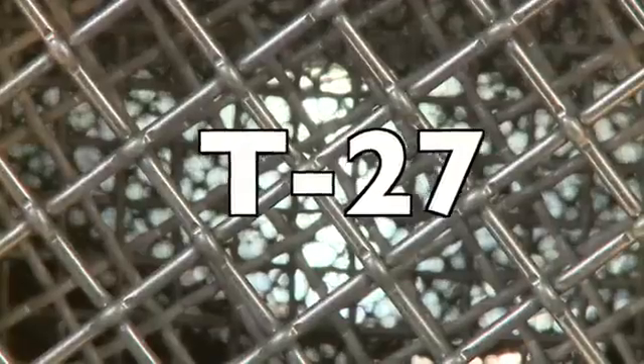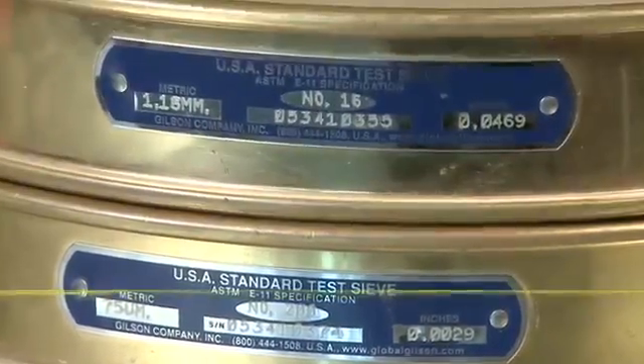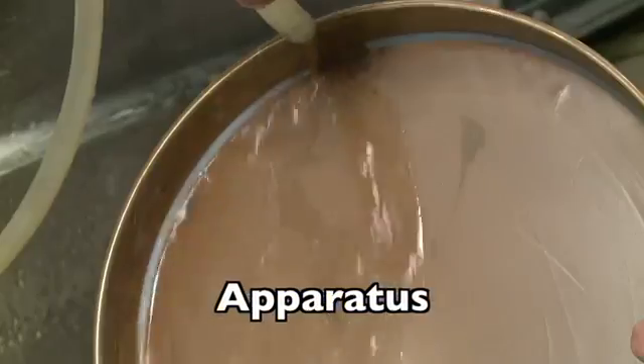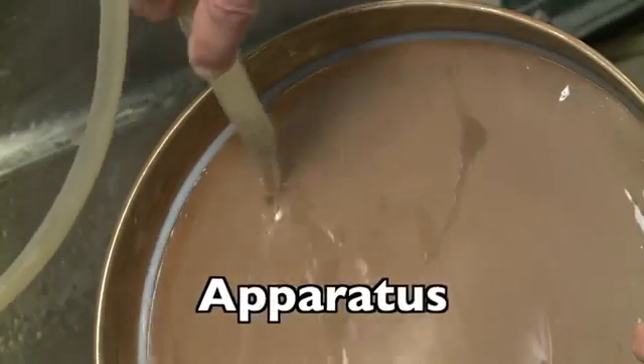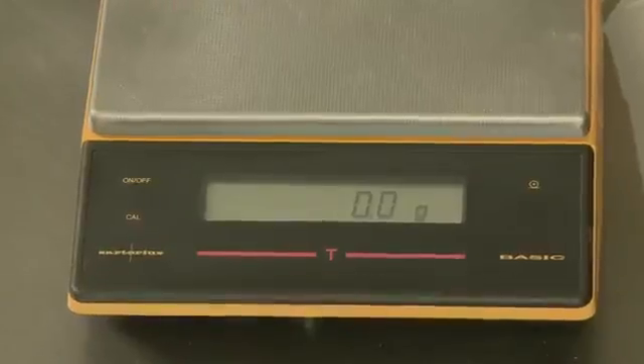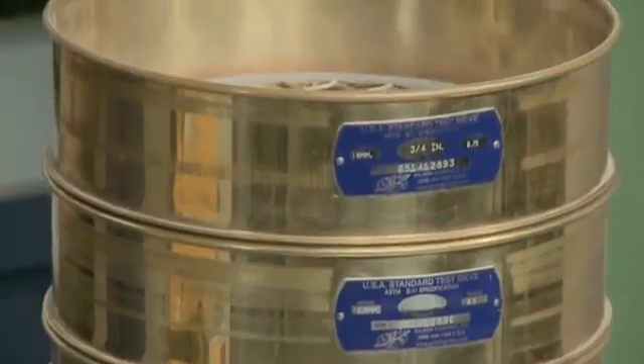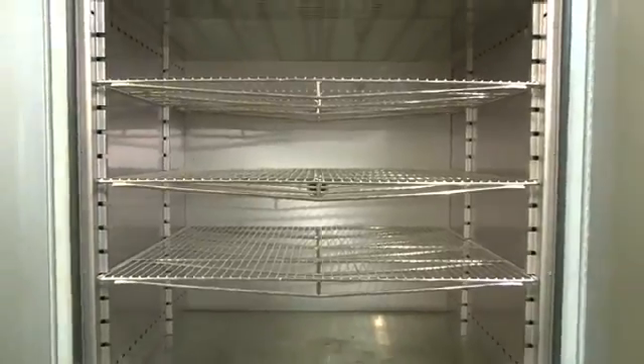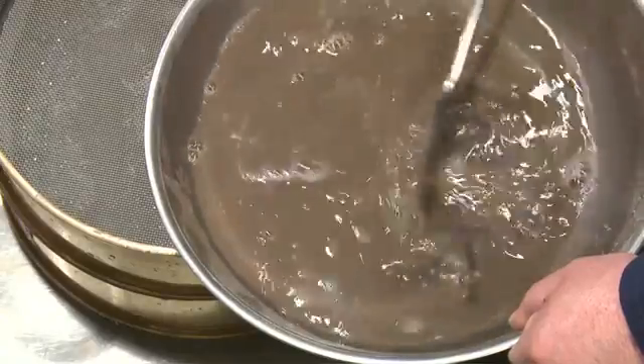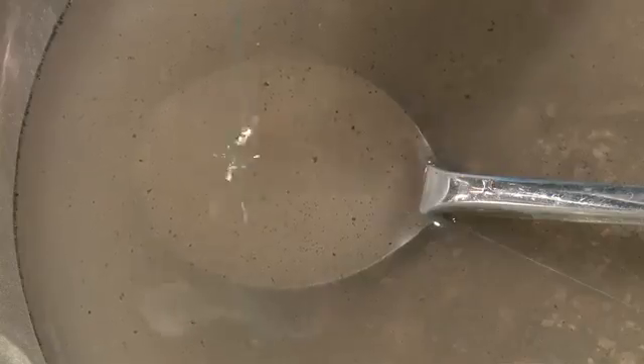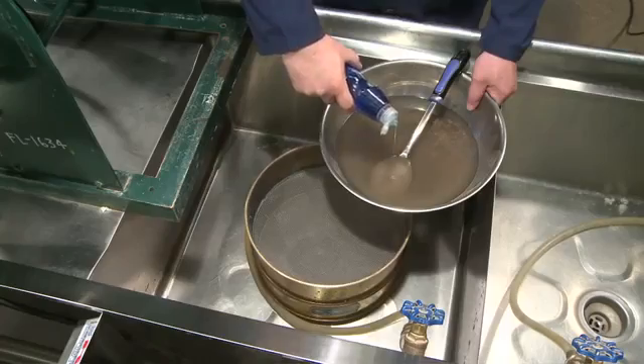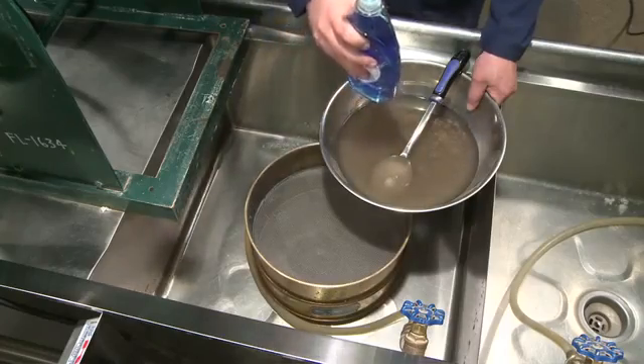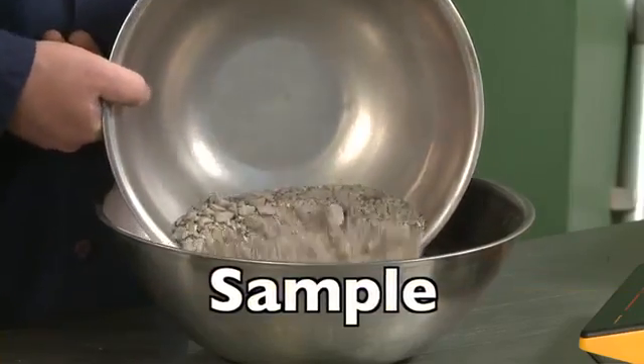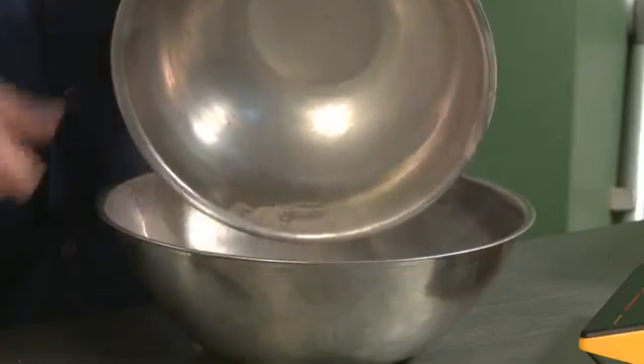sieve analysis. For this test, you will need the following equipment meeting the criteria specified in Section 4 of the standard: a balance, sieves, a mechanical sieve shaker, a drying oven, a suitable container and stirring utensil, and a wetting agent, usually dishwashing detergent. The test is performed on the entire extracted sample.